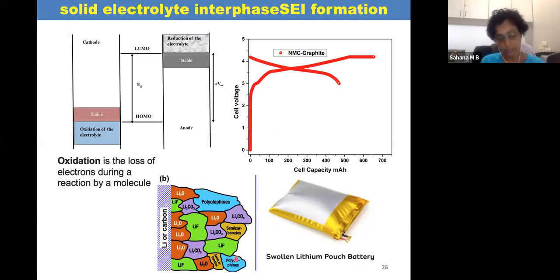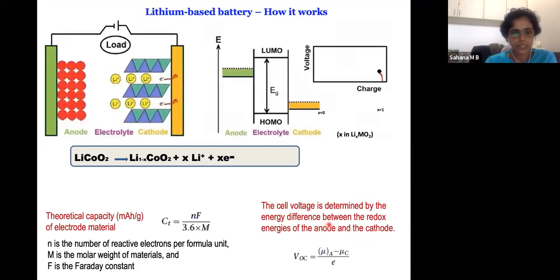But even in a very bad pouch cell or any of the cells, the gas evolution during that time can be very high. So you can see one of the swollen lithium ion pouch cells. Now this is just after the first cycling. If it forms like that, the safety of the cell will not be very good. So we need to remove the gas out of it and then again seal it, so that after the formation cycle, now what happens is,